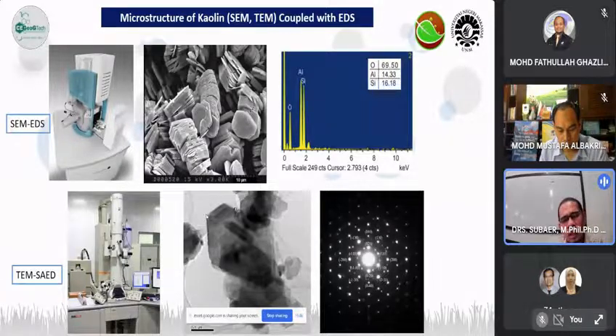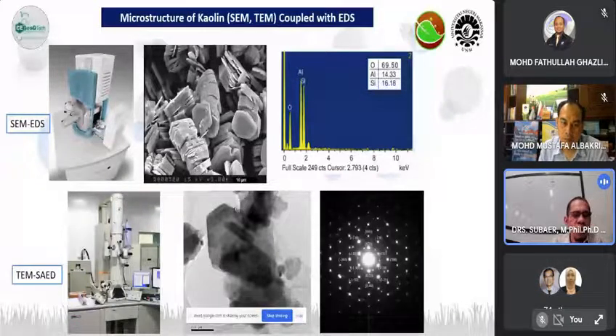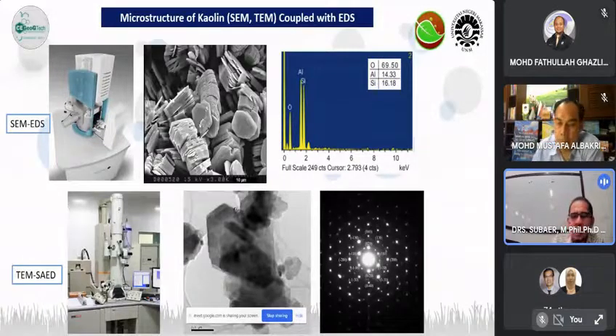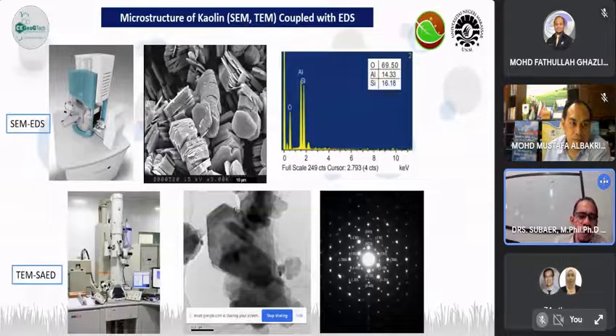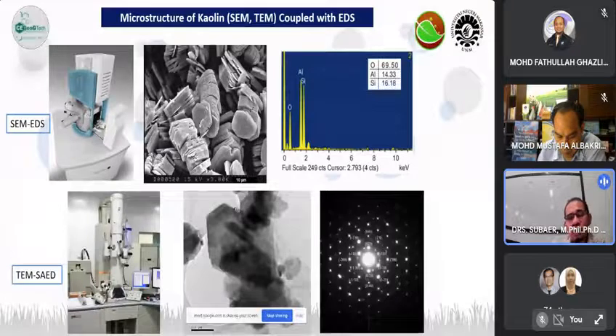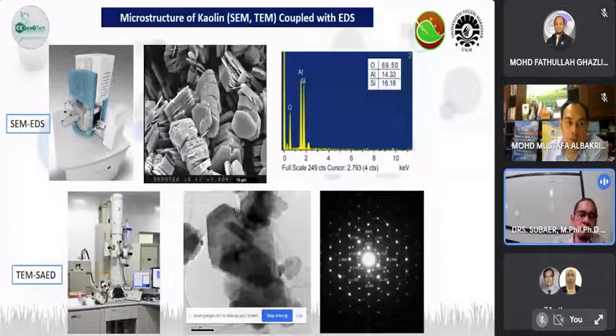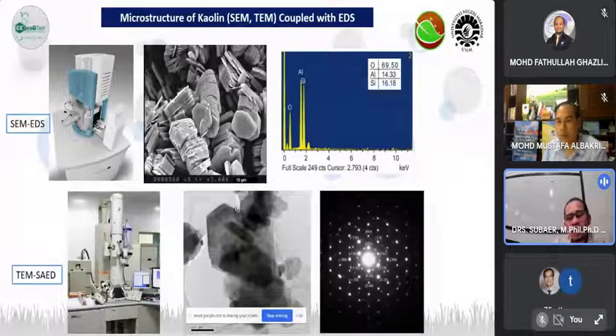And then we studied the morphology of kaolin, and we needed a lot of effort in order to get a very nice crystal appearance of kaolin that can be published, because the preparation is one of the most crucial things when you study things by using scanning electron microscopy. So you see the morphology of kaolin forming a hexagonal system with a thickness less than 1 micron.